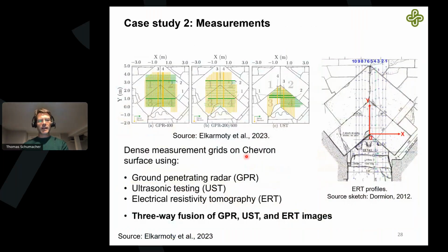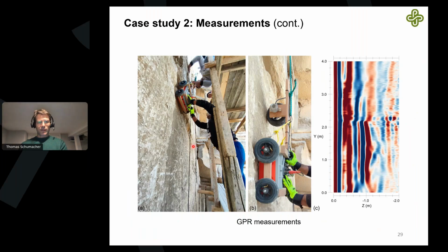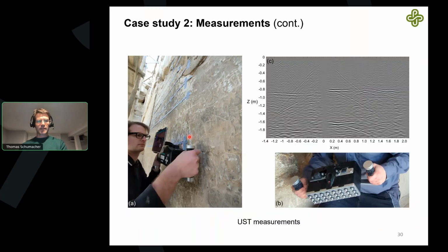We went there, we applied radar, ultrasound with the same tools that I just introduced. We also used electrical resistivity tomography, which gives you an indication of the electrical resistance of the ground, the underground. These three techniques were applied to these chevron blocks. You can get a sense of the size of these blocks here. This is over 2 meters wide. So this is the application of radar applied in the vertical direction. So that was sort of pulled up by a cart. Here's one radargram showing a strong reflector at about 90 centimeters depth. This is ultrasound, again, same device that I showed you, applied in the horizontal direction here in this case. You can see at a depth of about 90 centimeters, again, a very strong reflector showed up.